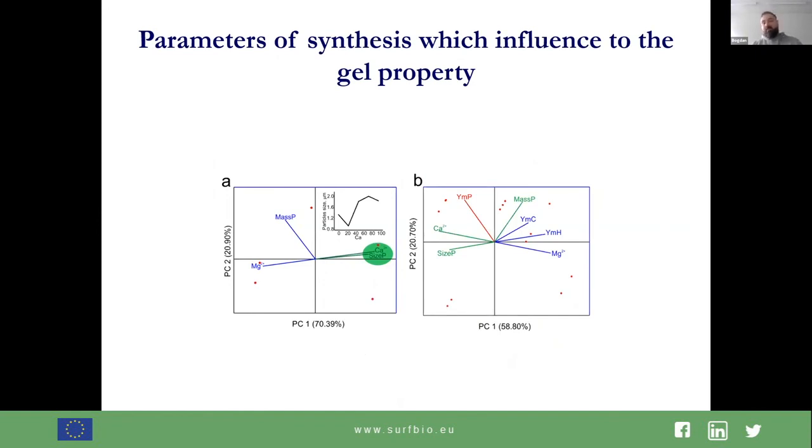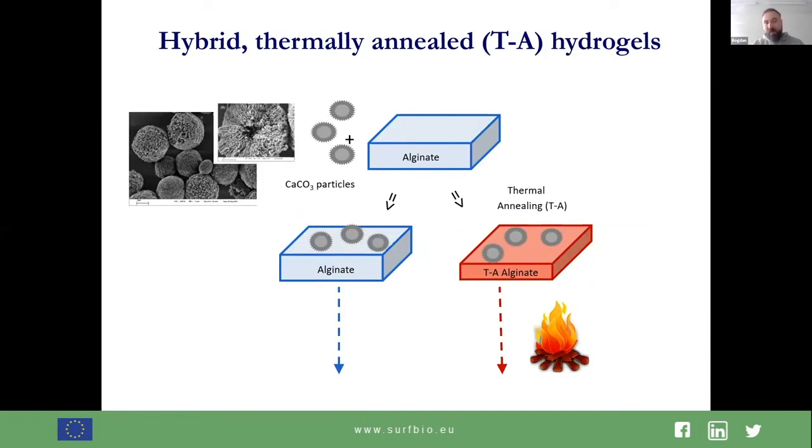And if the size of the particles is so important, what influences the size of the particles mostly? And we understood that the size of the particles increases if we have much more calcium in it. In this case, the total picture is like this. If we have more calcium in the initial system, we have bigger particles, maybe more mass of particles, more size of particles, in which cells grow better and provide better hydroxyapatite.